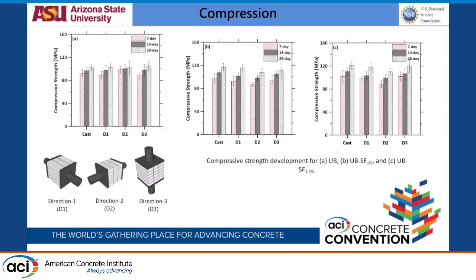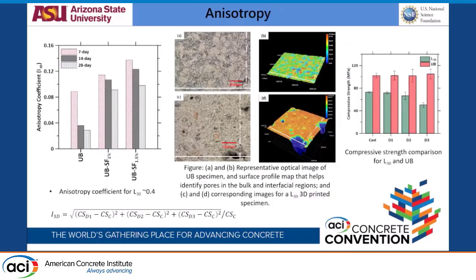Another thing is that we have multiple filaments in the same system. If you have just a single filament of the total width, you will not see the interfilament effect, and the interfilament effect is quite significant in printed elements, as we have observed in normal strength as well as UHPC mixes. Based on these strength values, we wanted to see what the anisotropy in these elements was and why. On the left, you see an anisotropy coefficient calculated from the three-directional strength test. For UB at 28 days, we are in the range of 0.03 anisotropy coefficient.